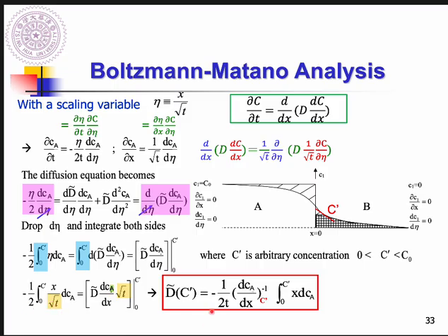So you got a negative 2t term here, and you also got the integral term, copy here, the integral term. And the only thing left on your right-hand side is here. So I move it to the left-hand side, and it will be the reciprocal of the concentration gradient at C prime, because it's at C prime. So now I finally successfully got the D of C prime, which can be expressed as shown here.